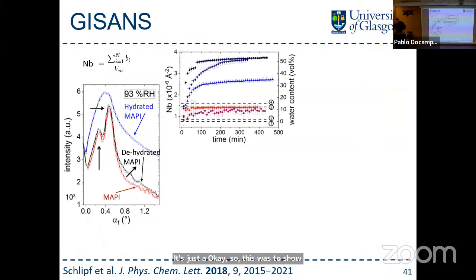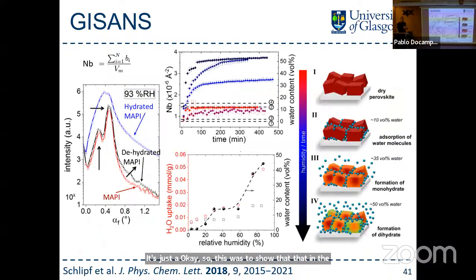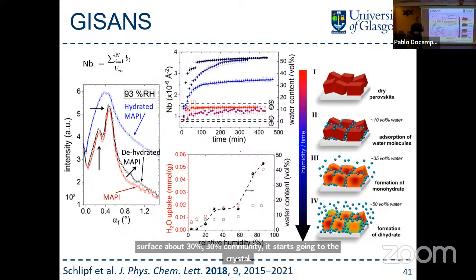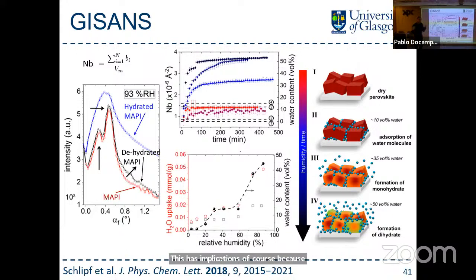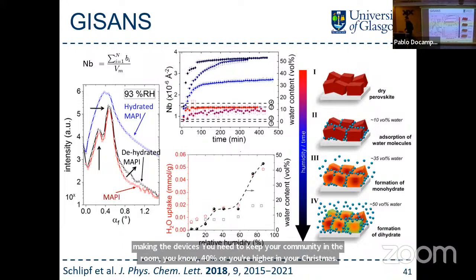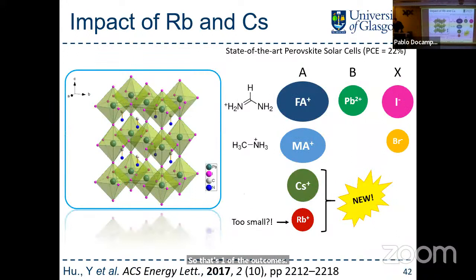Anyway, this was just showing that this indeed happens. And we did a bit more work looking at the specific mechanism. What we find is that depending on the relative humidity, it's a bit of a staircase. Below 30% humidity, water just absorbs on the surface. Above 40% humidity, it starts going into the crystal. This has implications, of course, because when you're making these devices, you need to keep the humidity in the room below 40%, or you're hydrating your crystals. So that's one of the outcomes from this work.